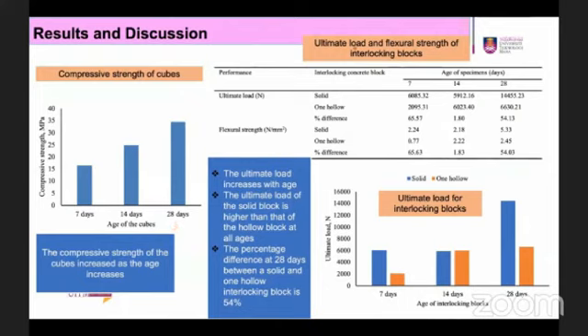And then this one is the result for ultimate load and flexural strength of the interlocking block at 7, 14, and 28 days. This one is the graph for ultimate load versus age of interlocking block. From these tables and figures, we can summarize that the ultimate load increases with age, and the ultimate load of the solid block is higher than that of the hollow block at all ages. The percentage difference at 28 days between the solid and hollow interlocking block is 54%.